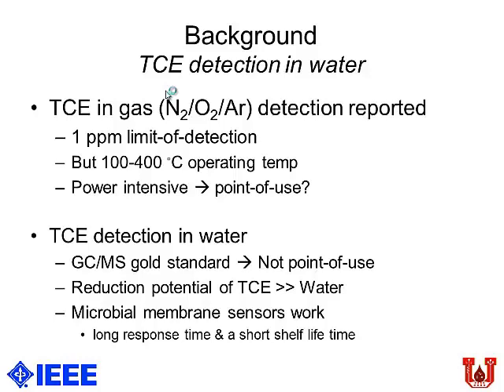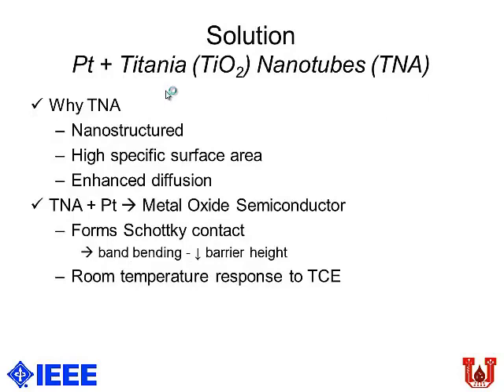The reason there are not many trichloroethylene water-based sensors is that you cannot have conventional electrochemical sensing based on TCE, because the trichloroethylene reduction potential is much higher than water. So if you apply a voltage, before you see a signal for trichloroethylene, water would just break up into hydrogen and oxygen. There's been some significant work on microbial membrane sensors, basically embedding microbes which convert TCE and detect it, but these have a very long response time, and they don't have a long shelf life. So that's why we came up with a solution which we think works.